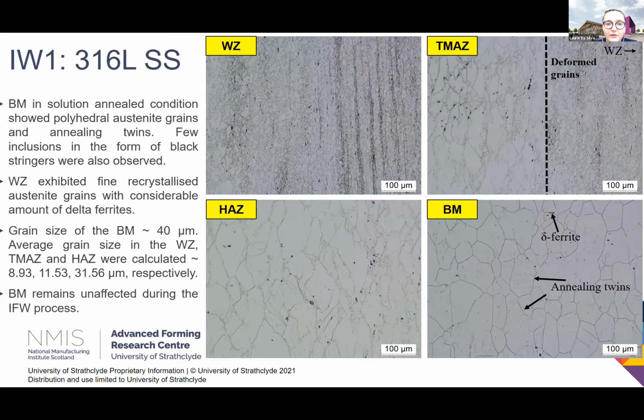If we look more at the individual alloys' microstructure, in the base material we have a solution annealed condition, so we have really nice austenite grains with some delta ferrite and some nice annealing twins. There's not that much difference between the base material and the heat affected zone in terms of grain size. However, as soon as you get to the weld zone up here, you see very fine recrystallized austenite grains and a larger amount of the delta ferrite material. As you go to the thermomechanically affected zone, towards the weld zone on the right-hand side, you see more deformed and recrystallized grain. And on the left-hand side, it's more similar to the heat affected zone. But we don't see any evidence of columnar grain growth or any of the microstructural defects that we would expect from the current manufacturing route.